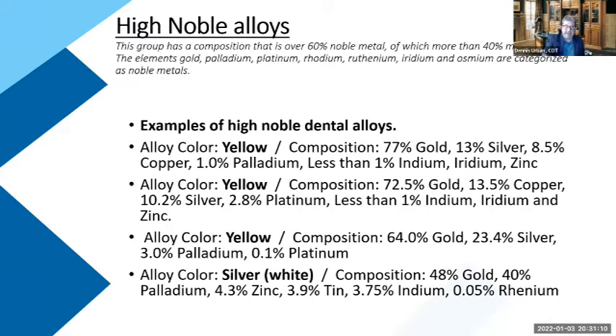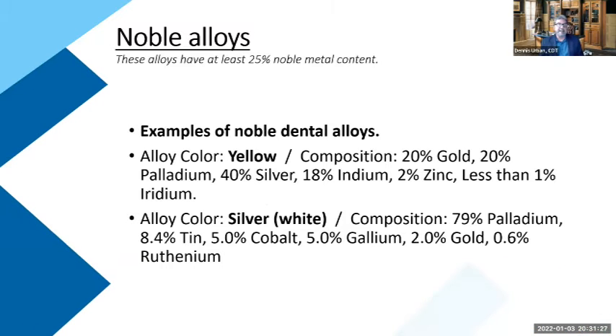So you can see the differences down here. Look at alloy color and composition. You can go anywhere from 77% gold all the way down to 48% gold. But as long as you have those other metals in there, it has to be 60% noble to qualify as high noble. And the noble alloys, which are most widely used when we're doing PFMs, have to have at least 25% noble metal content. These are just a couple of examples I can see here: 20% gold, 20% palladium, silver, indium, zinc.